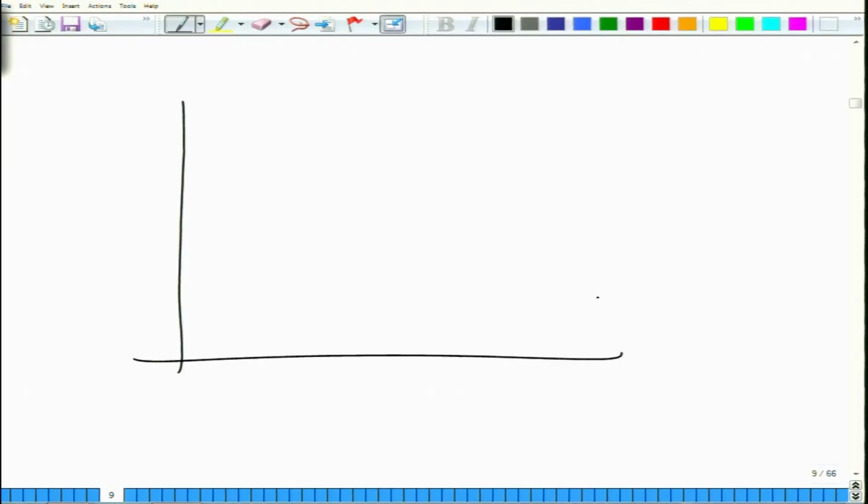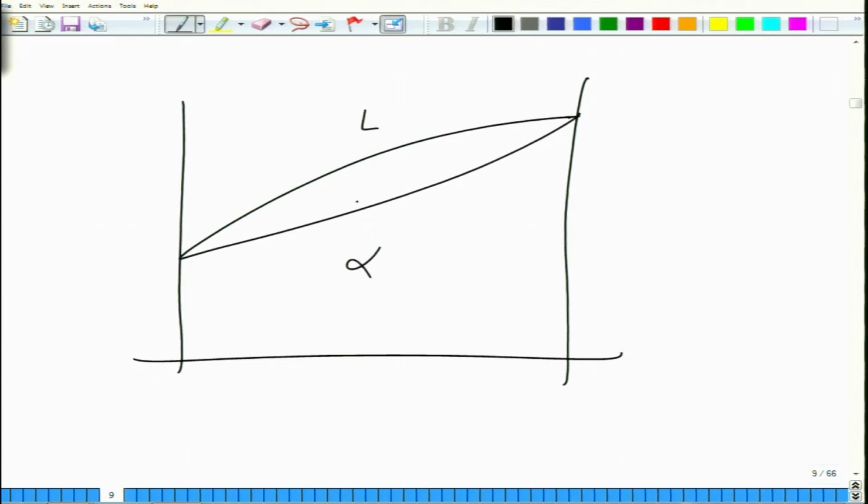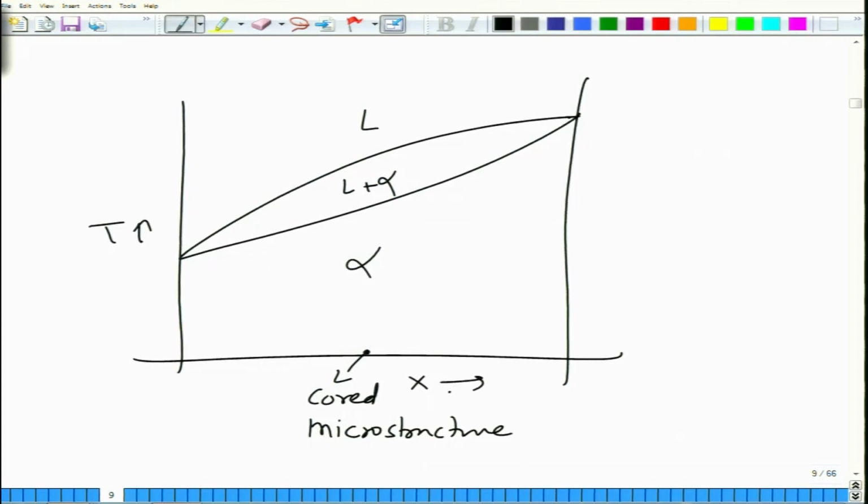So if you have this as a phase diagram, let's say you had a microstructure which was a cored microstructure. Again, temperature, and this is composition X. So the cored microstructure is heated to temperatures which are just below solidus. There you don't cross the liquid region. So you go from point A to B. Hold at T less than T solidus